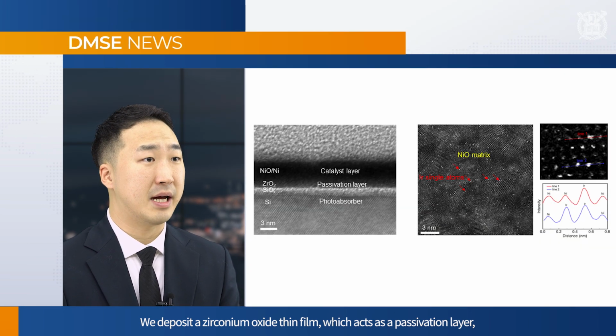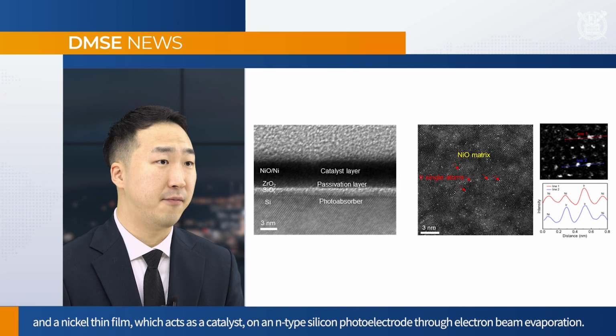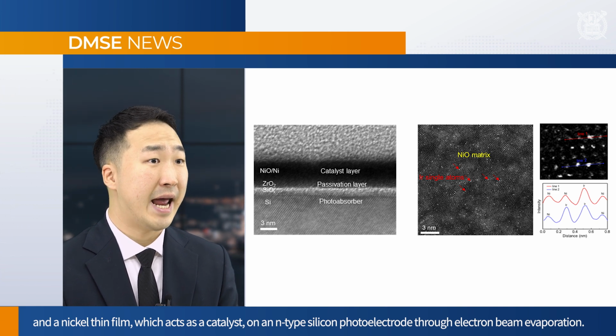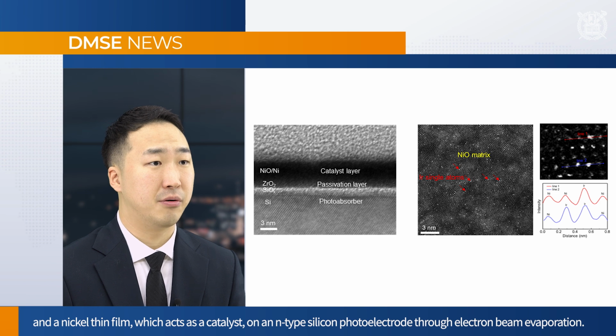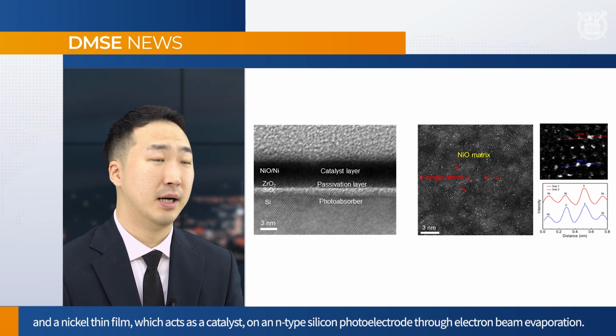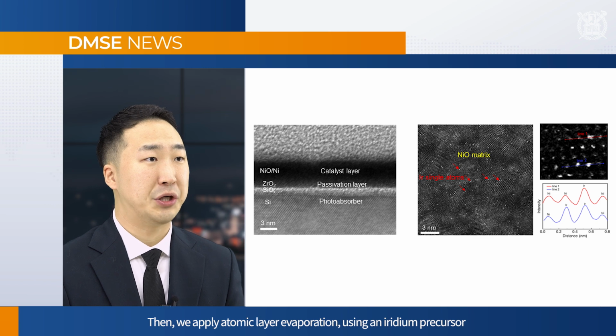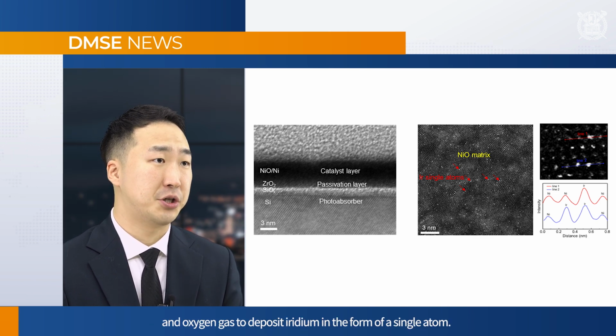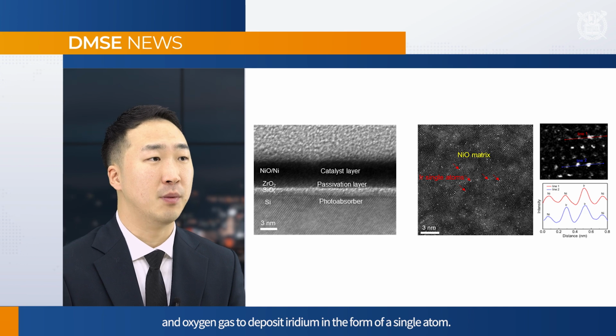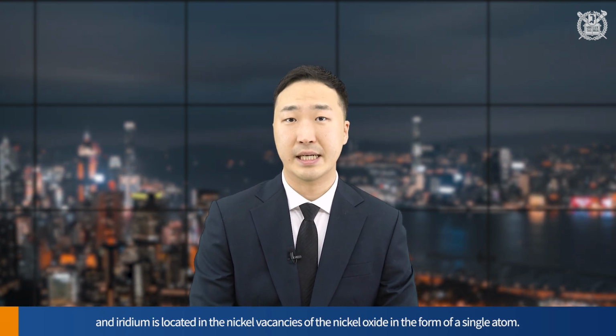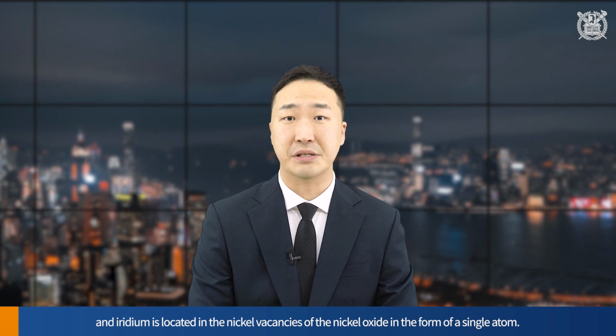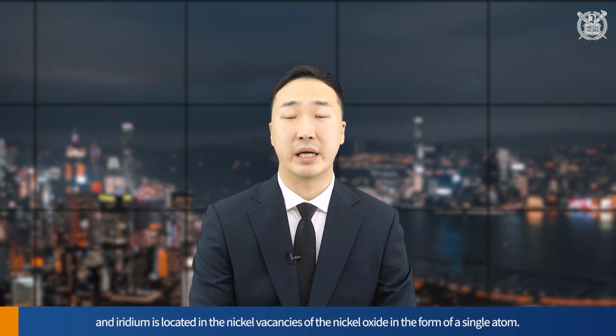The team's development is detailed as follows. We deposit a zirconium oxide thin film which acts as a passivation layer and a nickel thin film which acts as a catalyst on an N-type silicon photoelectrode through electron beam evaporation. Then we apply atomic layer deposition using an iridium precursor and oxygen gas to deposit iridium in the form of a single atom. In this process, the nickel thin film reacts with oxygen to form nickel oxide on the surface, and iridium is located in the nickel vacancies of the nickel oxide in the form of a single atom.